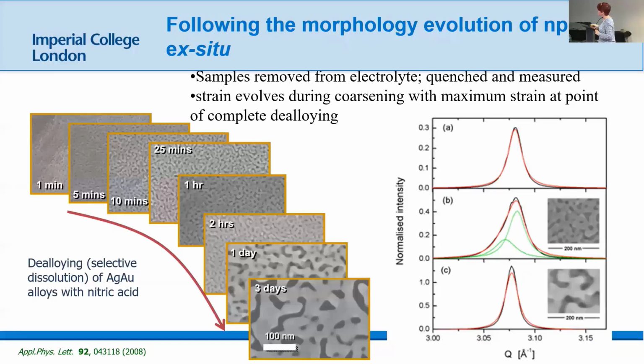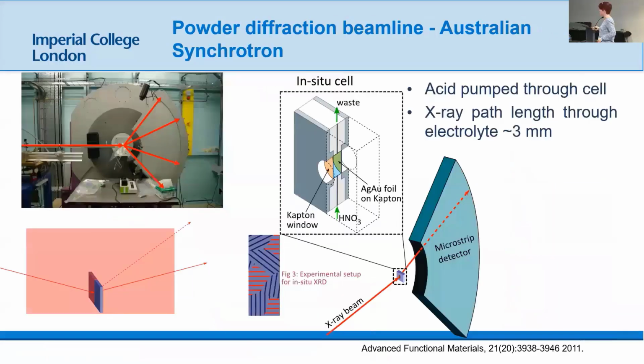This is the kind of structure that you get from SEM imaging afterwards, and you can see the longer you leave your foil in the acid, the more coarsening behavior you get. But what we also saw with simple diffraction, and those of you with good eyes will see, is that when you start and when you finish, you've got a beautiful symmetric peak. But in the middle, at intermediate pore size, there's an asymmetry in that diffraction. That means we're getting a split in the material, with two regions that have different strain. And this is not just the composition changing; it doesn't map what you would predict from compositional change.